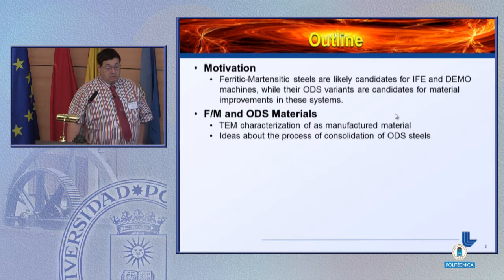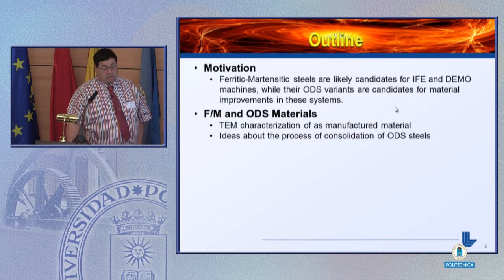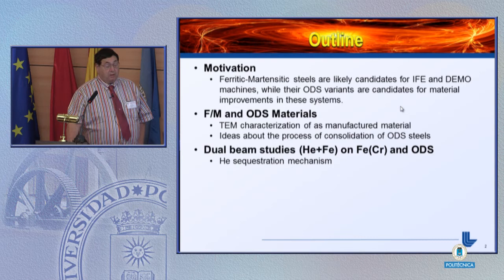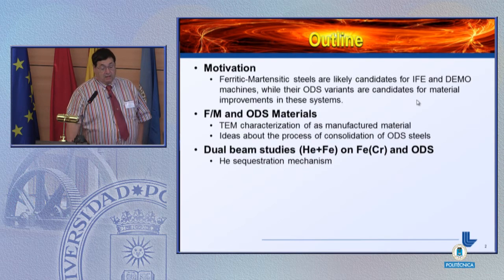Our approach for looking at these materials has been the use of TEM characterization of as manufactured materials, where we developed some new ideas about the consolidation process for these ODS steels. Our primary way of testing materials is to utilize ion beams. Ion beams allow us to accelerate the aging process in these materials by as much as 3 or 4 orders of magnitude over what they would see in an actual fusion environment. We use both a dual beam, and when I say dual beam, I'm referring to helium and iron ions.